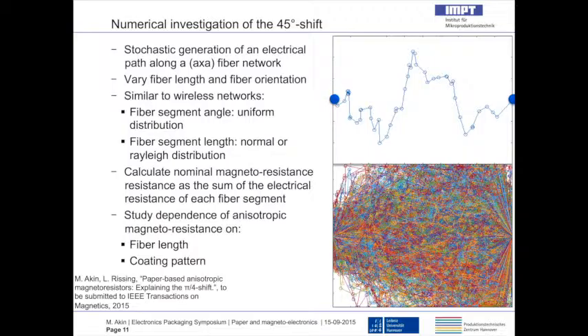That's what I call a segment, and that magneto-resistance adds up to the overall magneto-resistance. Similar to how wireless networks are modeled, we found that a uniform distribution of the fiber angles and a normal distribution of the fiber length give you basically the most realistic representation of the paper surface, from what I've seen in SEM graphs or micrographs. So we studied the magneto-resistance as a function of the fiber length and the coating pattern.